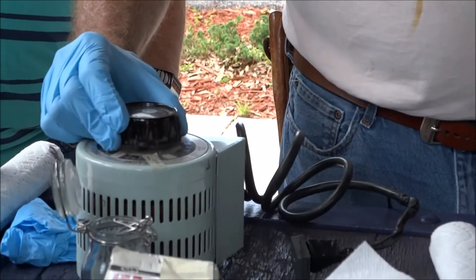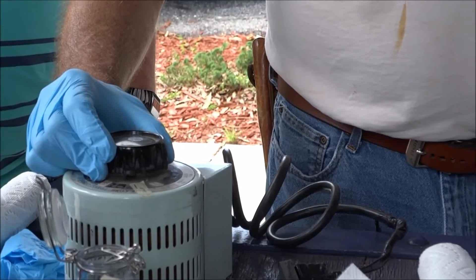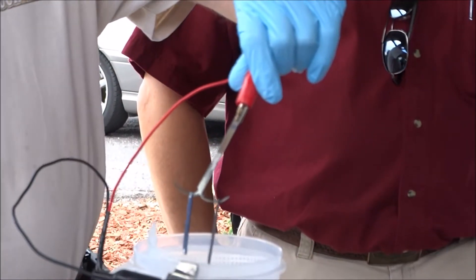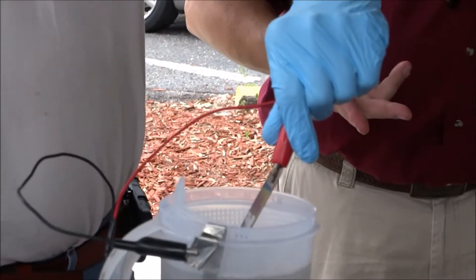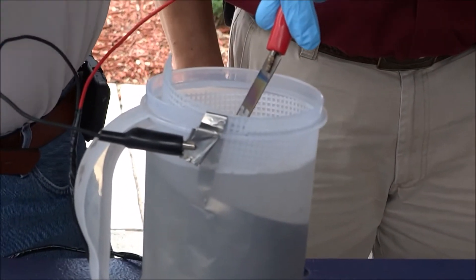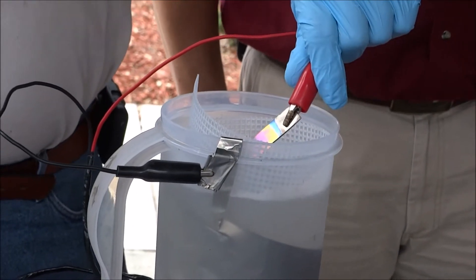Right about 24 volts AC starts getting colorable. Look at that — just that fast! No torch, just that fast. Now if you leave it in too long — no, you can just keep it in there, nothing is going to change as long as you don't change the voltage. It's all about the voltage. It's all going to stay the same.